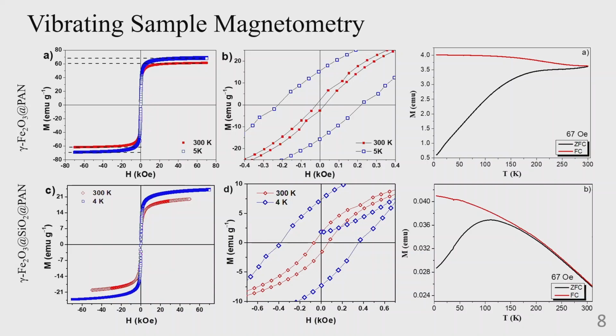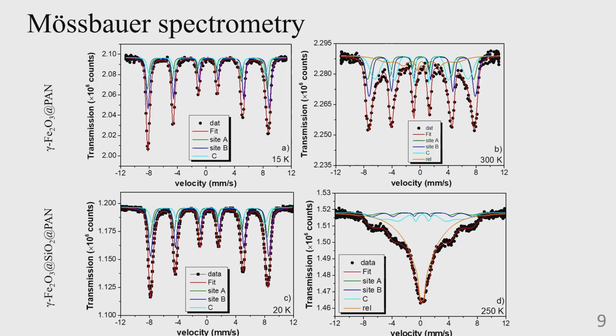And the zero field cooling and field cooling curves measured under a DC applied field of 67 oersted, as can be seen in the figure, exhibit broad maxima extending above room temperature for the single core shell and around 110 for the double core double shell sample. This maximum suggests that the particle size distributions are different in both samples, and some local method could bring additional information. And finally, the Mossbauer spectrometry,